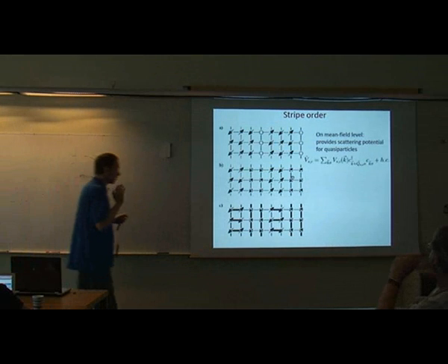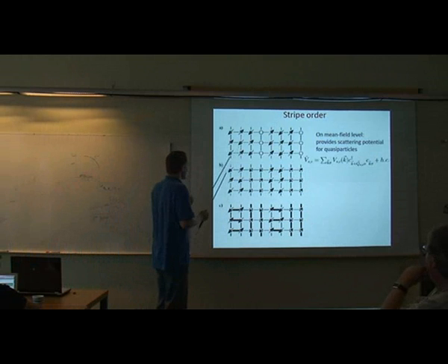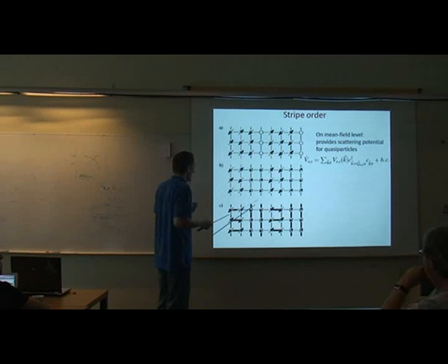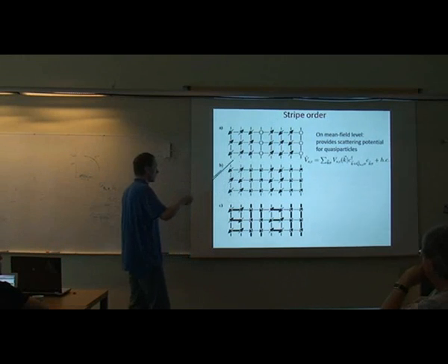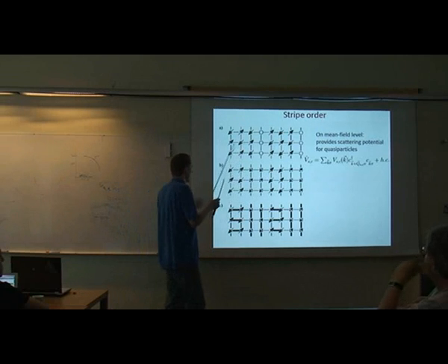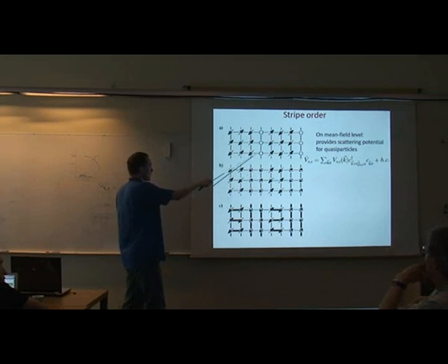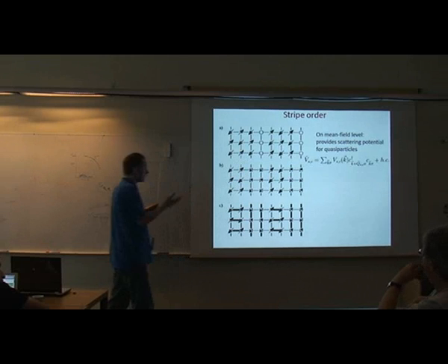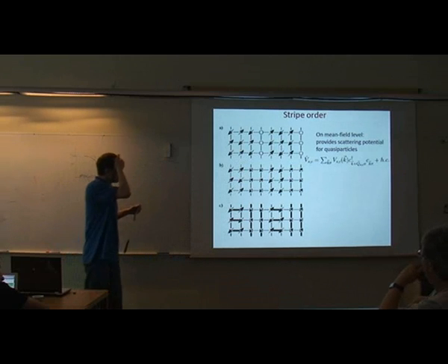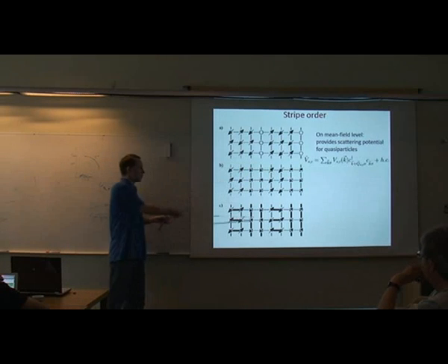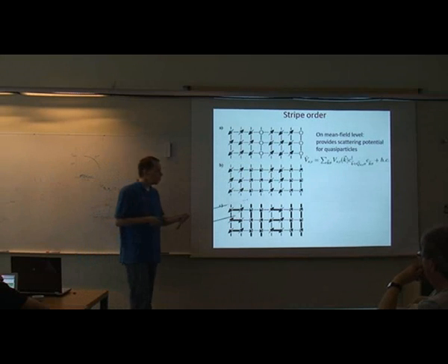Other patterns that I also will consider are possibly you can also modulate spin and charge density in this fashion. That's seen in lots of materials based on lanthanum strontium copper oxide. There's lots of details. The basic thing is this pattern is symmetric with respect to the atomic sites, whereas this pattern is symmetric with respect to the center of the bond. That's why it's called bond-centered and site-centered. The essential thing you have to ask, what does this pattern do with the normal state quasi-particles? That will be of interest to me.